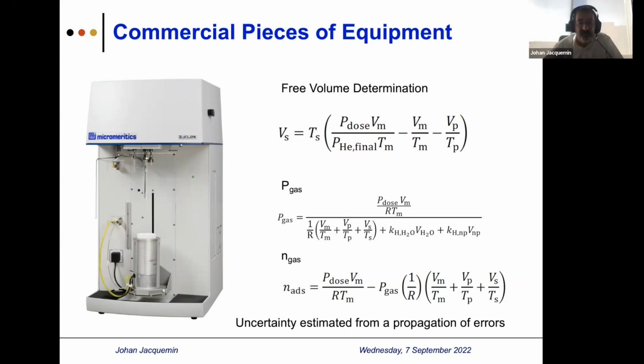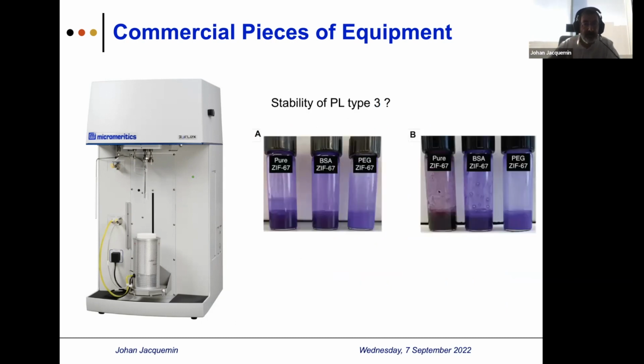to then check its solubility, normally in solid, but then they moved to porous liquid. And basically, porous liquid looks very fantastic if you read this Nature paper. However, there are some issues, such as the non-stability of some zeolite imidazolate frameworks in water, causing problems with long-term stability, and also the dispersion. Could we say that a dispersion is a stable phase? That is a question that I ask you directly, frankly.